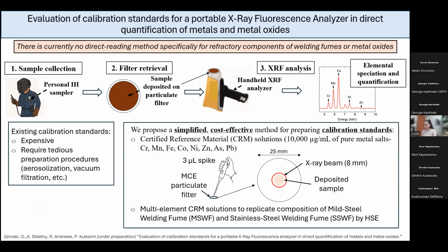standards. And how I did that, you can obtain from the market some very highly concentrated, certified reference material solutions that contain pure metal salts. You can get this for maybe $90 per sample. And you can create your own serial dilutions by using just one pipette. Very simple preparation procedure. And then you take a filter, any filter that you want to use as your substrate. I use the MCE particulate filters because they are widely used, particularly for metal detection. And I spike 3 microliters of all my solutions on the center of the filter.